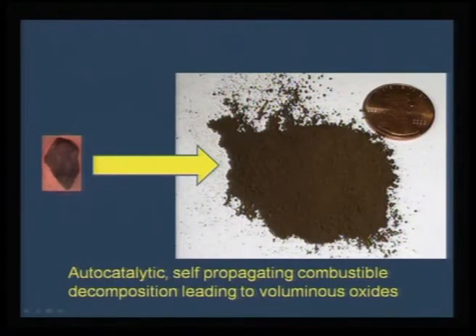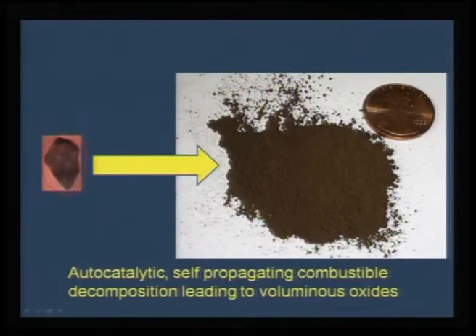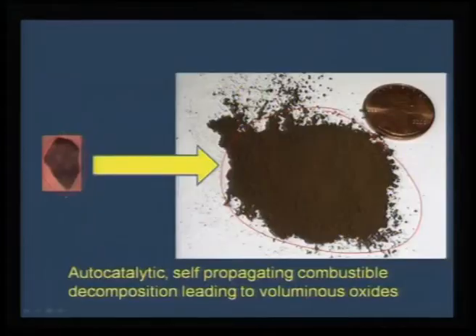Suppose the crystals of these hydrazine carboxylates are taken to be like this. In fact, if you mix these two salts and put the hydrazine carboxylate ligand, in 2-3 days time you would be able to isolate beautiful crystals like this. And if I try to heat this crystal, you would get this much of powder. In our regular practice, we know that if you take any compound and heat it, it will only reduce in size. But what happens here is there is an autocatalytic and self-propagating combustible decomposition which leads to a voluminous oxide. That is the beauty of these hydrazine carboxylate precursors.